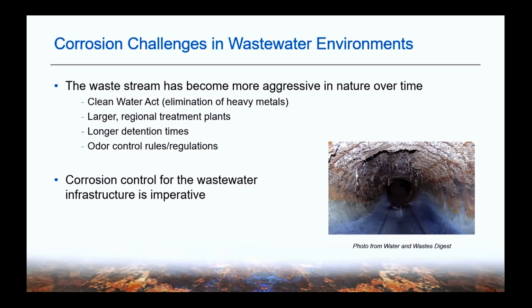There are some other things that have led to this. One of the major shifts was a move to larger regional treatment plants instead of having smaller treatment plants in each community. A lot of these developments see a treatment plant as a nuisance. They don't want to have a wastewater treatment plant near them. So we started seeing more of a shift to these regional plants. But with that, the sewage had to go a further distance, so you had longer transport times, and you also had longer detention times, which allowed the waste stream to become more septic and in turn more aggressive. This will be the common theme we'll talk about today: corrosion control in the wastewater infrastructure is imperative, because some of these areas of the system can get very aggressive and can break down a structure very quickly.